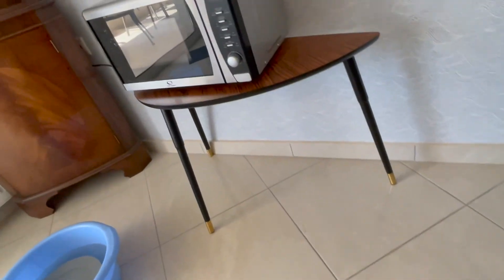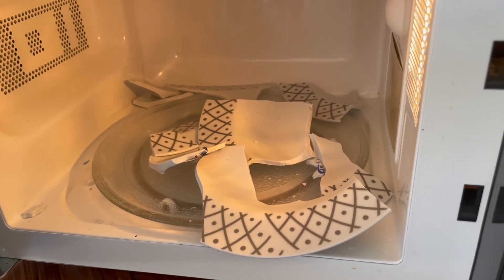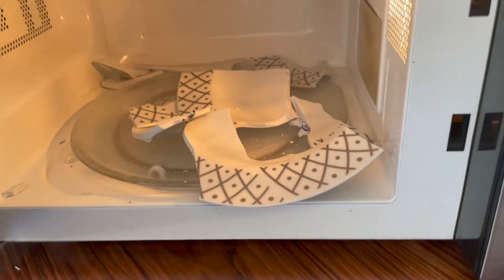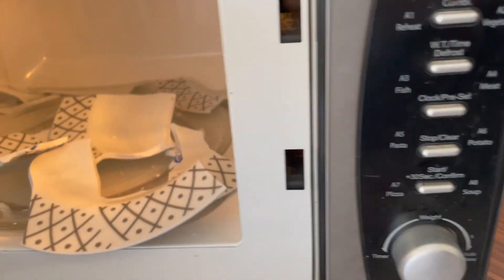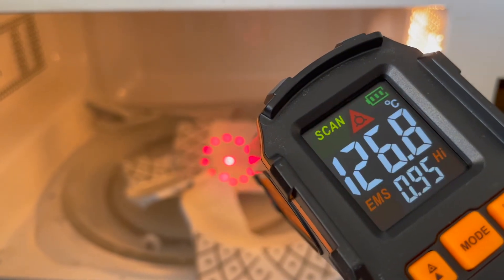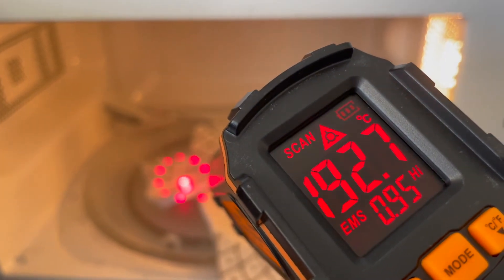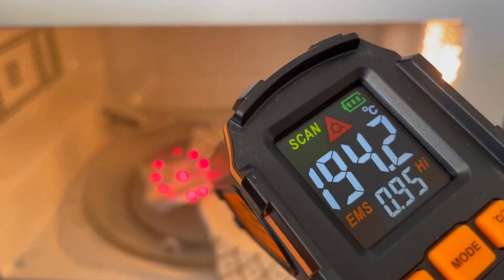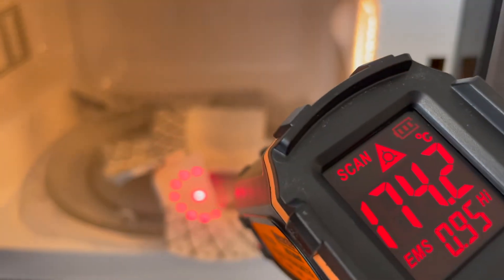When we heat the porcelain plate — remember there's no porosity, so there's no water in the plate — we're just heating the ceramic. And microwaves heat differently across an area, so you get hot spots and cold spots; that's why you have the turntable to try and stop this. But these hot spots and cold spots create terrible stresses in the plate, which causes its catastrophic failure as we see. And we can see those hot spots and cold spots and the differences in temperatures measured after the failure.